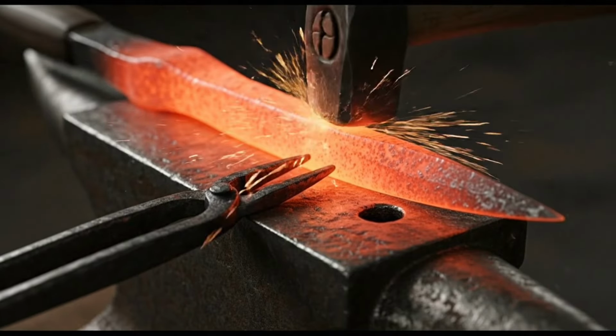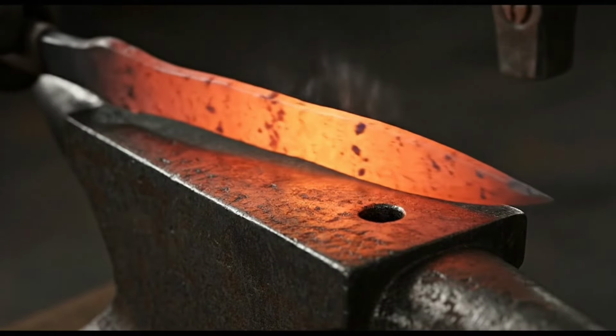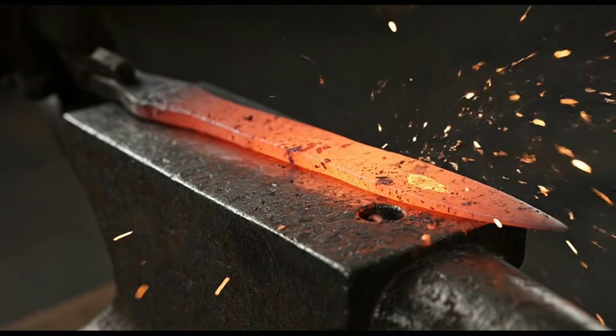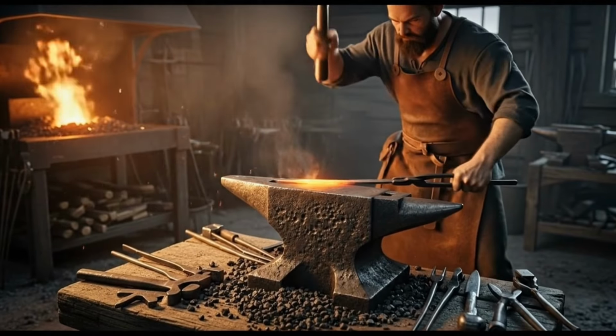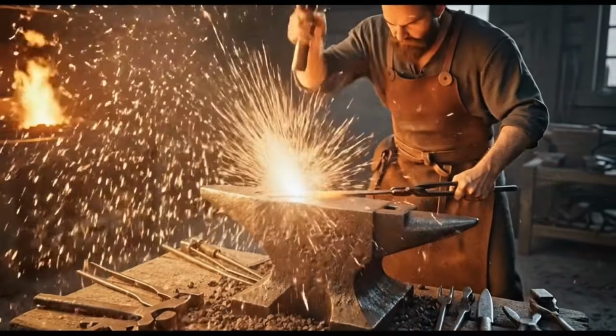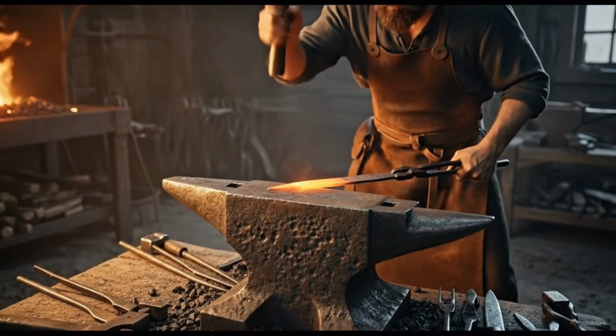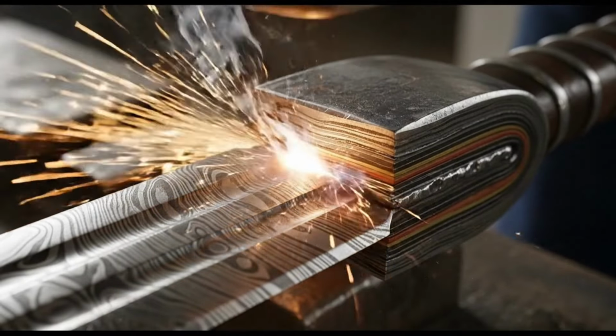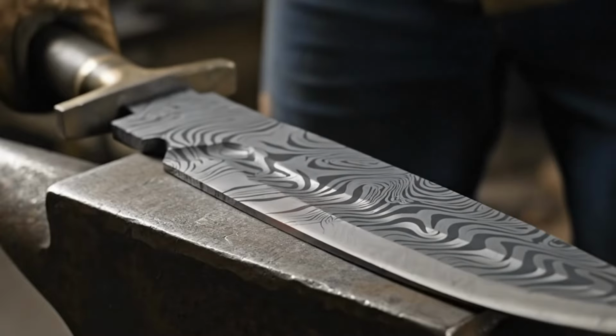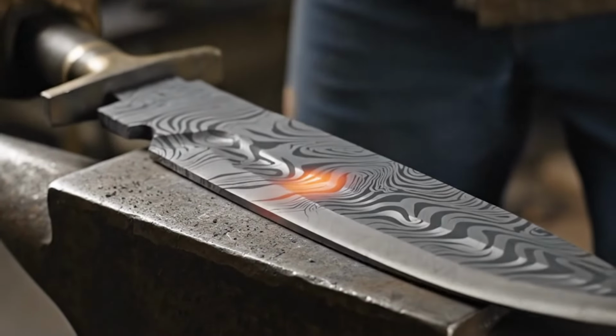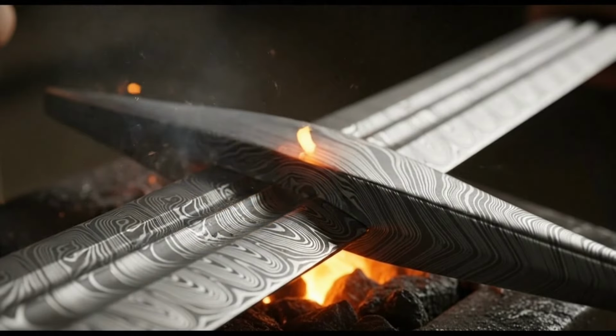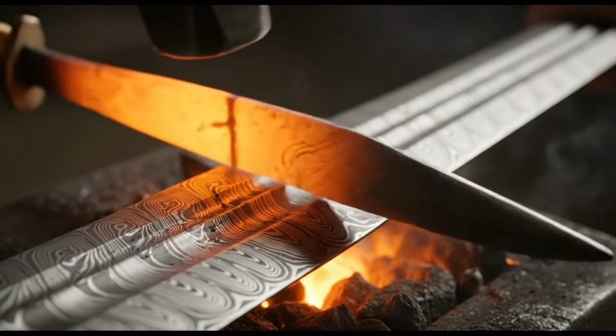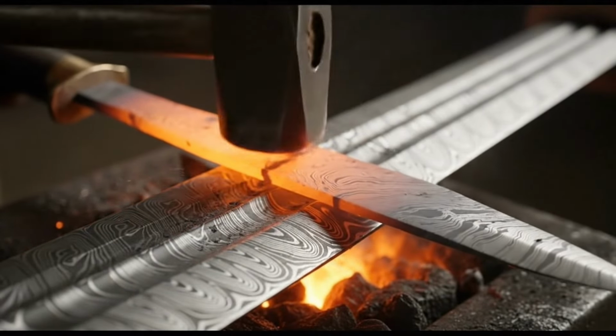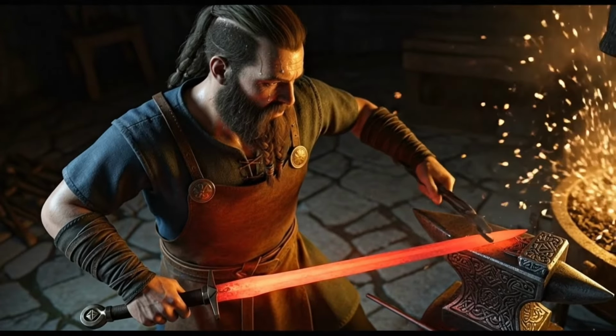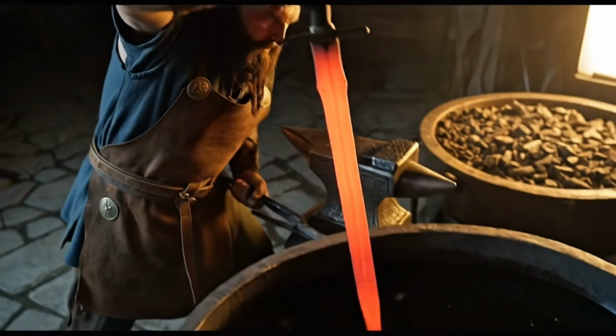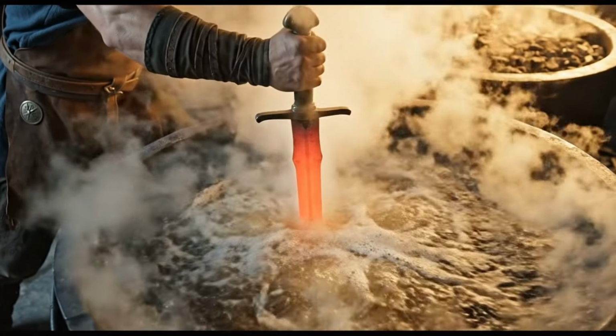This procedure required tremendous experience and vigilance. Excessive air and the entire mound would burn to ash, insufficient, and the procedure would halt. Calculations show that 4 to 10 kilograms of charcoal were required, producing 1 kilogram of iron, and obtaining charcoal in turn necessitated burning several times more timber. Producing a 1 kilogram sword could require felling several dozen mature trees. This means metallurgy was among the primary factors influencing landscapes. Around large settlements where smithing was actively practiced, forests could be cleared for many kilometers. This forced people seeking new timber sources or relocating production.